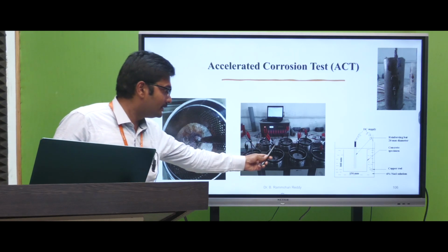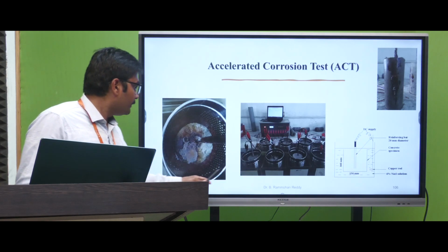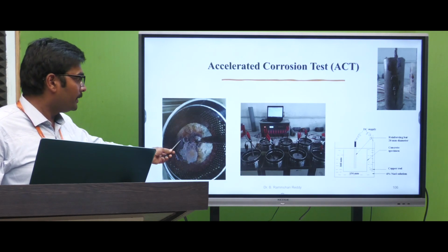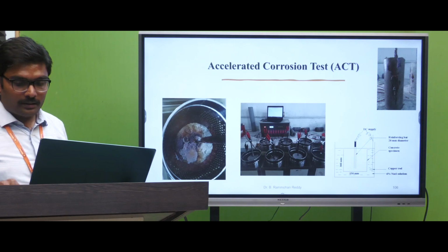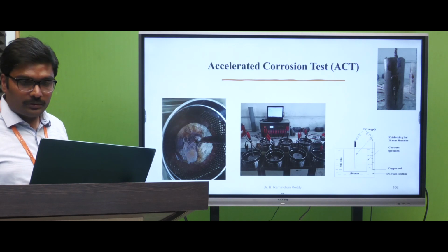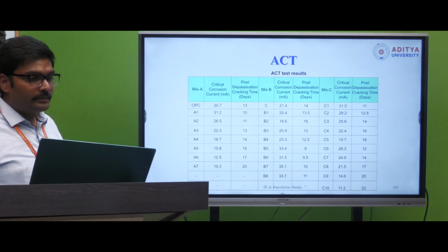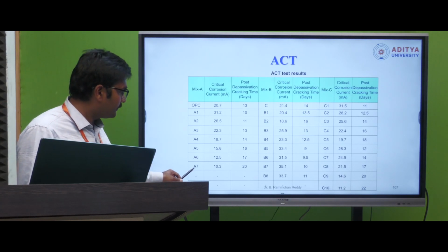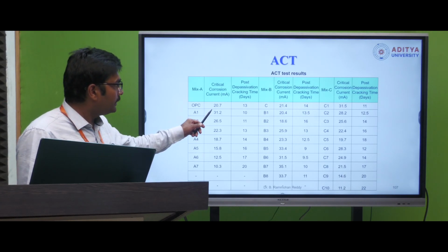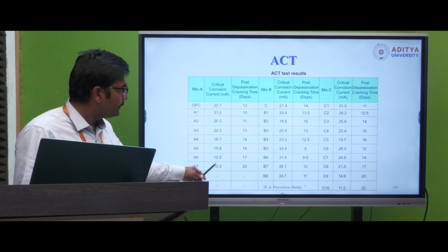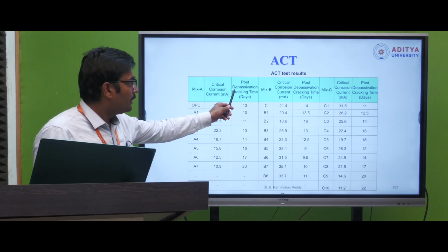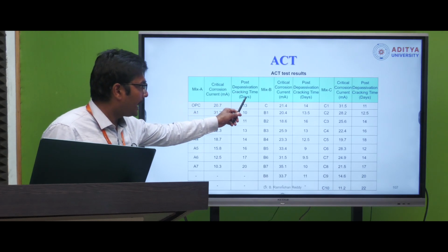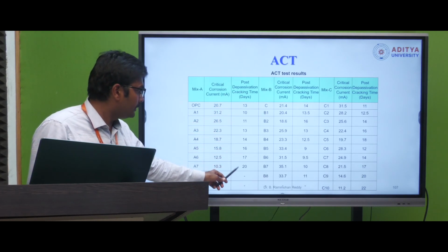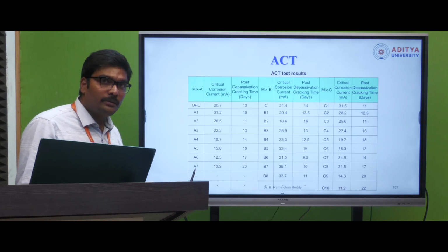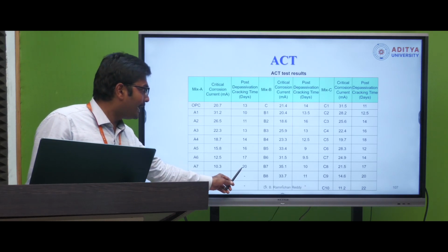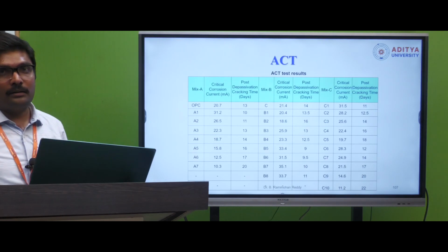of the concrete. So this is the total setup which we have made, and you can see the suffering of the sample under this NaCl solution. And the results are indicating, you can see A1 to A7. So the critical corrosion current is reduced, and also the depassivation or crack time, how many days, you can see here. A7, where more GGBS content is there, is taking a long time for the crack to appear on the sample.